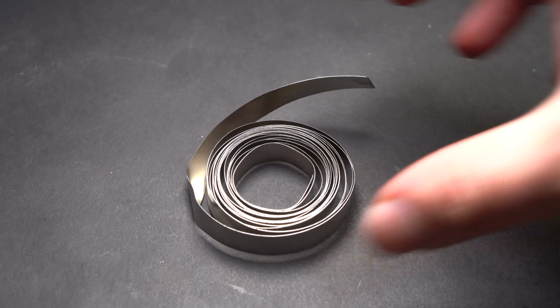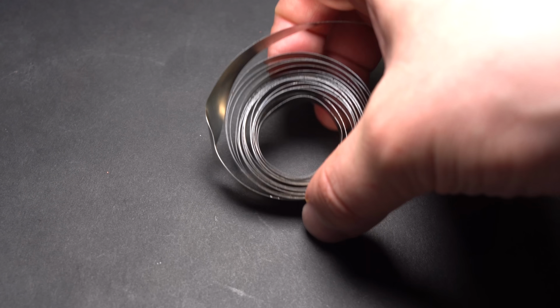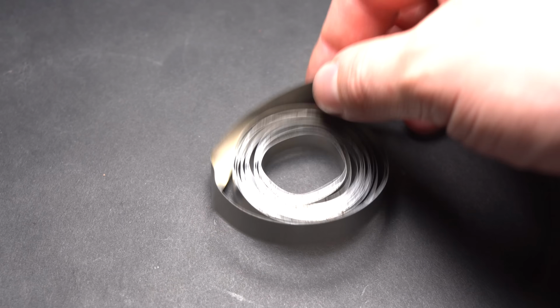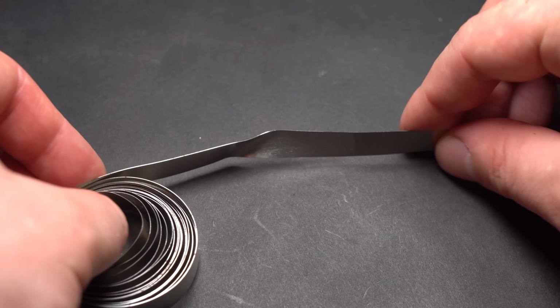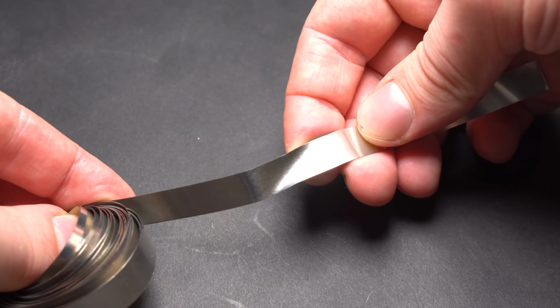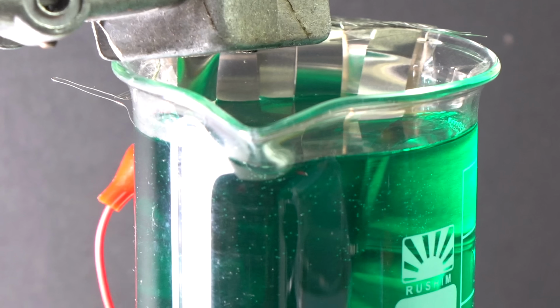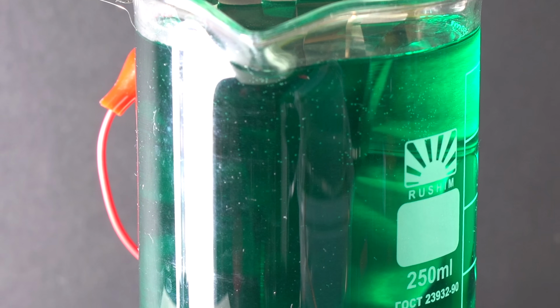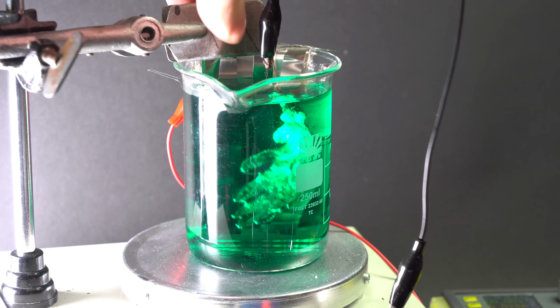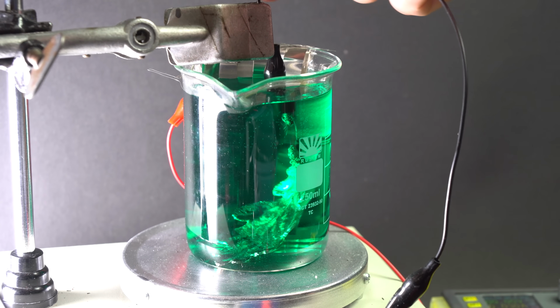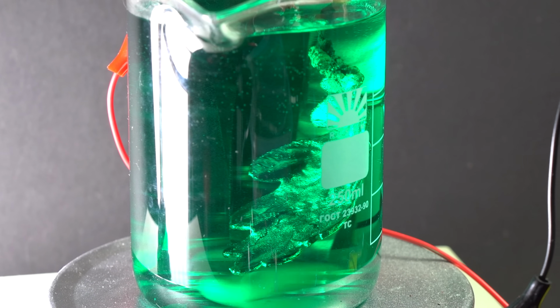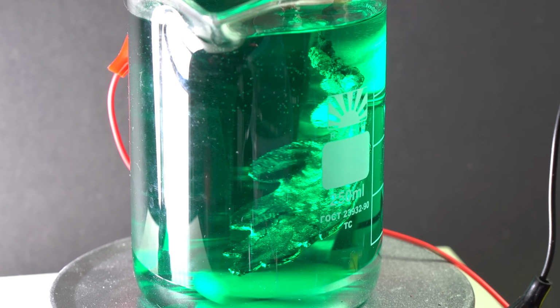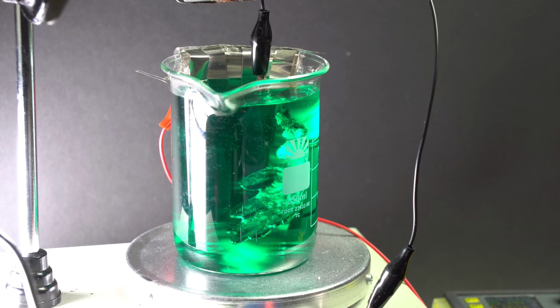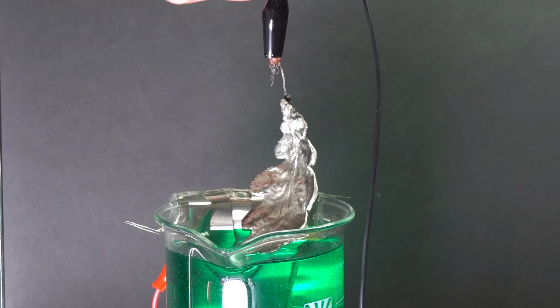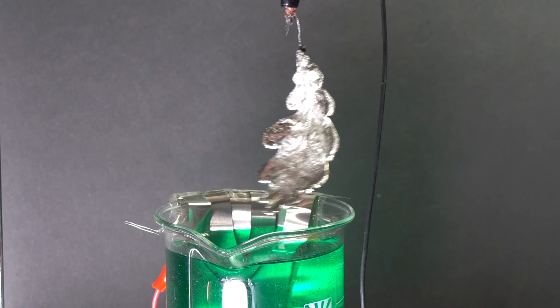I used a nickel strip as an anode, which I was sent by a Chinese manufacturer. I sliced the nickel strip into a few smaller strips and attached them to the beaker as anodes. After that, the copper leaf is ready to be plated with nickel. I set current to 800 milliamperes. It was a rather random choice. To my surprise, nickel stuck to the copper in an even layer and didn't come off. The whole process took about 20 minutes.